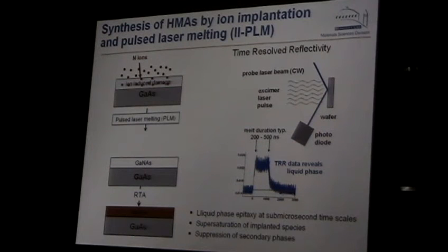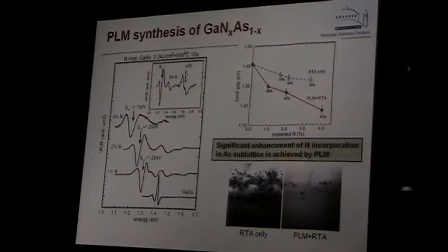We can compare the properties of this material grown by pulse laser melting and, let's say, by standard epitaxial techniques. And this material is not as good. Unfortunately, we have to admit that if you grow by epitaxial technique, it's better, but we can reproduce most of the properties quite well. We can improve it even further by so-called rapid thermal annealing. It's not as rapid as laser melting, but it is of the order of seconds, or 20, 30 seconds, or minutes, let's say.